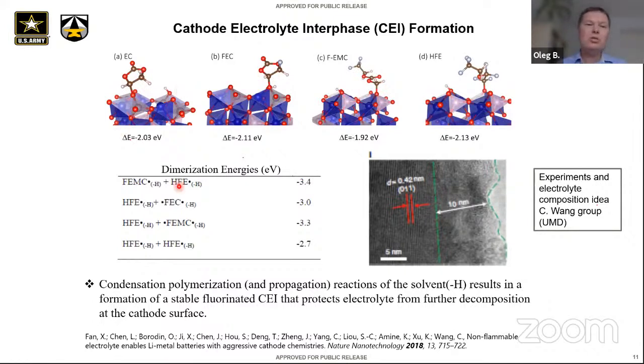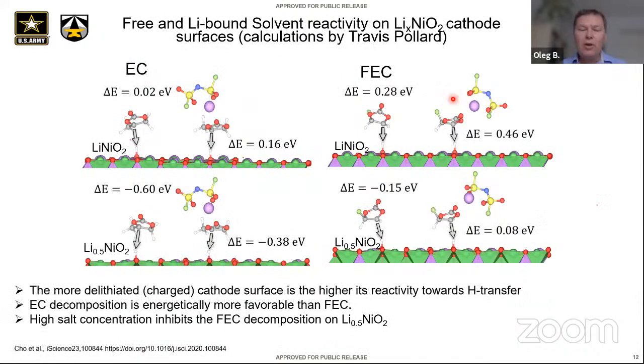But now we introduce something which has primarily all the fluorines, and that builds a heavily fluorinated interface, CEI, cathode electrolyte interface, which does no longer have the reactivity of protons, and it stabilizes. So that's what is shown here, that in this electrolyte, in the combination which they optimized, there was a good protective layer which allowed stabilization of this very, very aggressive chemistry. So with this in mind, I want to give more of a summary of trends which we did observe.